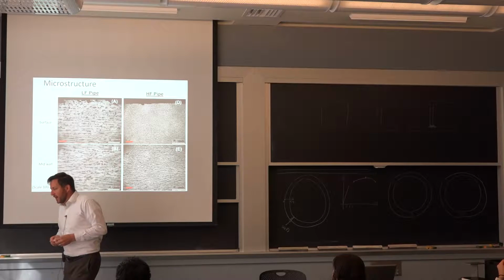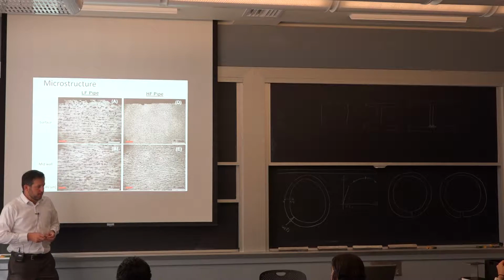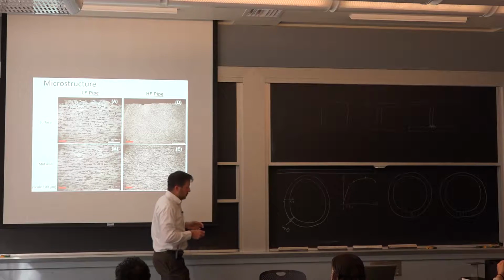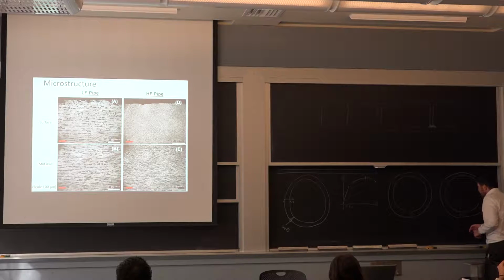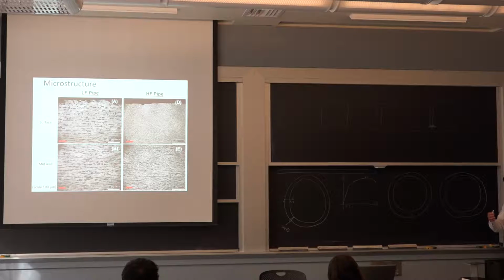It's not as big of a factor for the microstructure. If I stay very long at temperature in my annealing process, I can heal a lot of these residual stresses. We call it a stress relief treatment. Anywhere that there were a lot of stresses between the surface and the core, because at temperature my yield strength goes down so much, I can just deform and get rid of a lot of the residual stresses. So that is something that would happen on the second pipe, the one that has a different microstructure. If you cut it up, it's going to stay where it was. The pipe that was cold worked and welded, if you cut it up, it's going to open up on you a little bit.